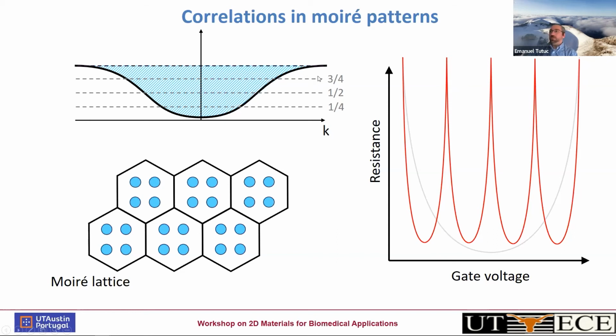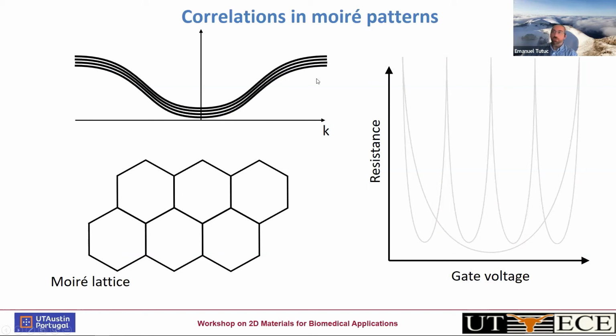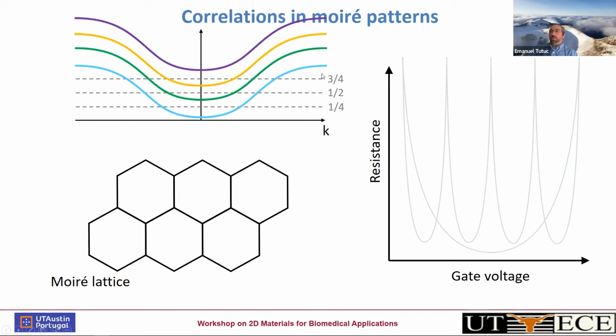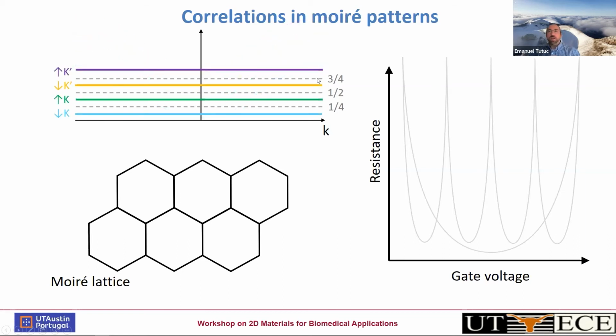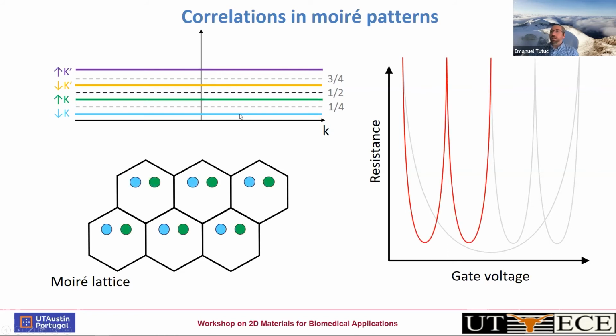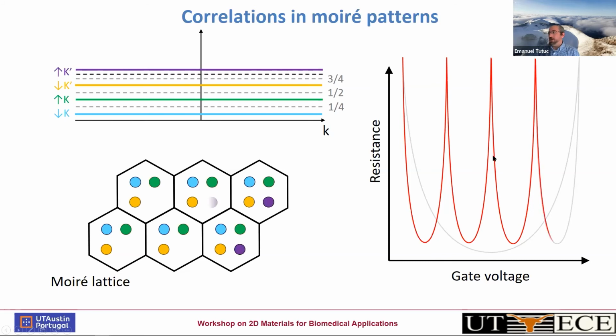And the way we can understand it is we can take this flat band, make 4 copies, 1 for 2 spin and 1 for valley. And then let's pretend that they're very flat. And then when we have these flat bands, but they're degenerate, something wants to break the degeneracy. And that something is actually electron-electron interaction. And we see this phenomenon in other instances. Whenever we have a degeneracy, any imperfection would like to break that degeneracy. In this particular case, electron-electron interaction wants to break that degeneracy. And as a result, these levels actually are split by interaction. And as a result, whenever we try to populate a moiré flat band, correlated insulators would emerge in the middle of the band. In this particular case, a quarter and half filling associated with the lifting of the valley and spin degree of freedom.